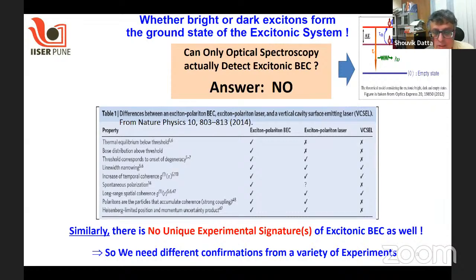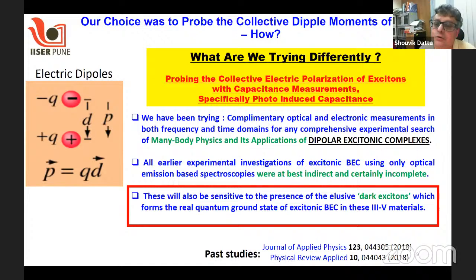However, if we understand that excitons, as electron-hole pairs, have a positive charge and a negative charge, they are a kind of dipole-like quantity. What if we try to probe the collective electric polarization of these excitons, the collective dipole moments, using capacitive measurement? That has been our approach for quite some years. We have been probing excitons in 3-5 semiconductor structures, including dark excitons, because capacitive techniques don't distinguish between bright and dark excitons, as long as they can probe the dipole moment by monitoring the collective electric polarization of these dipoles.